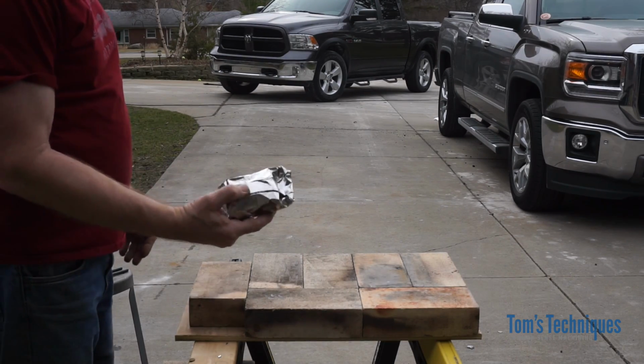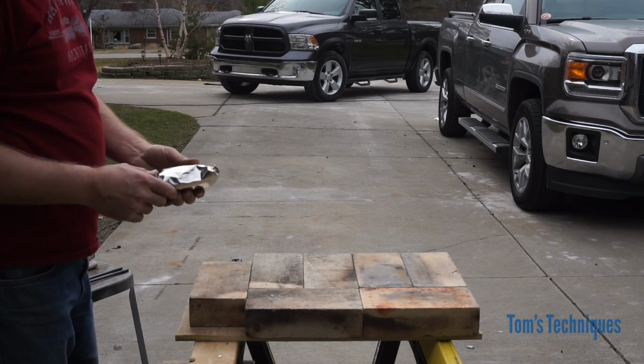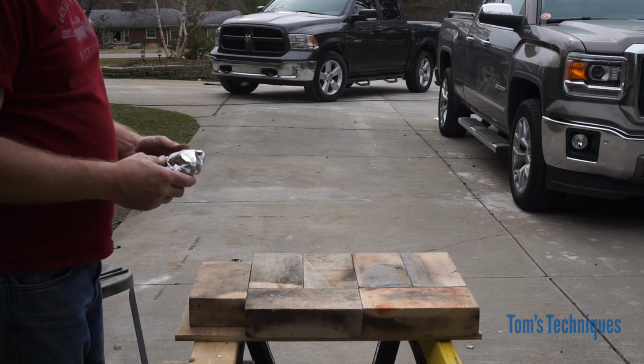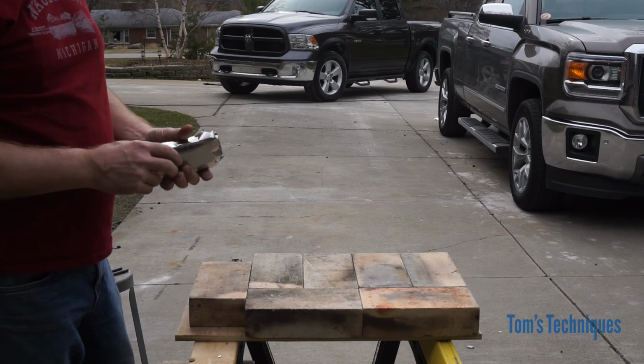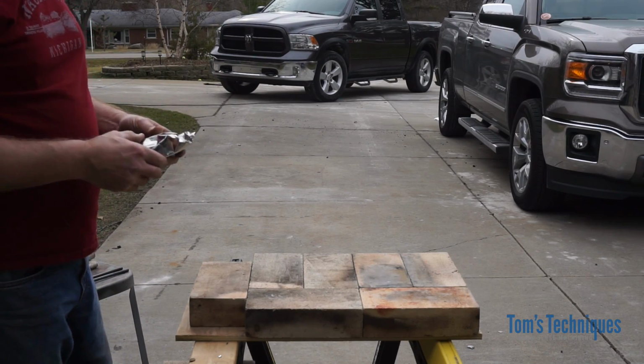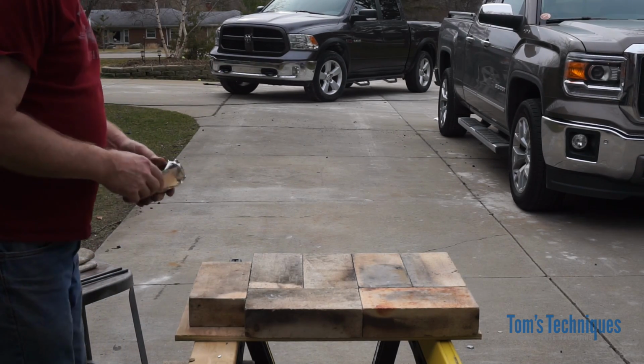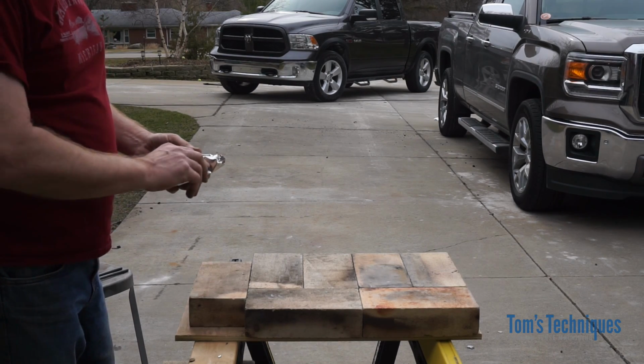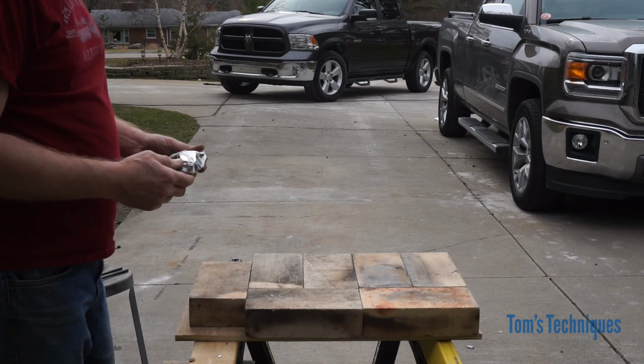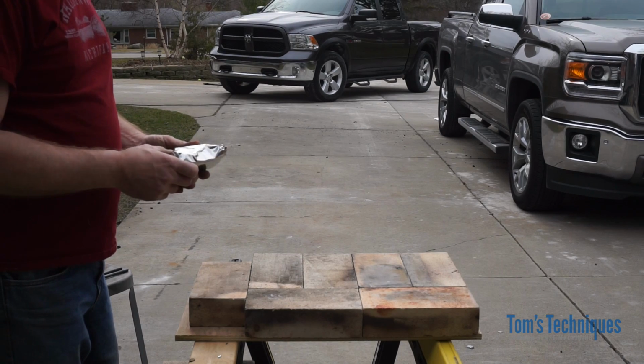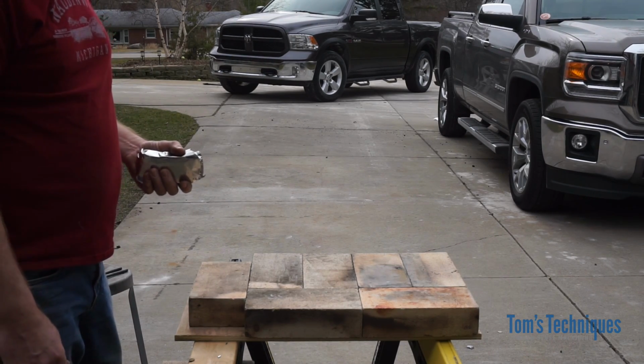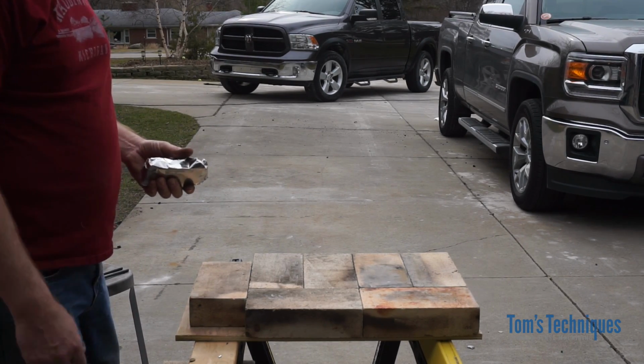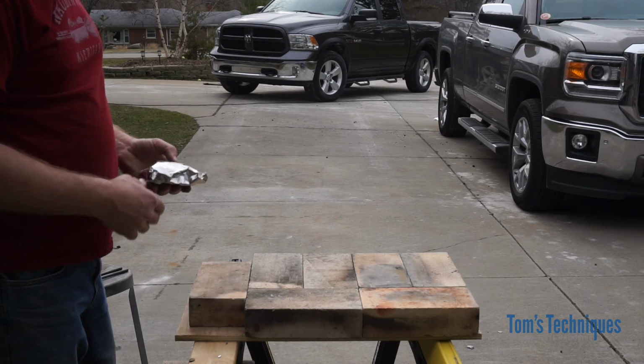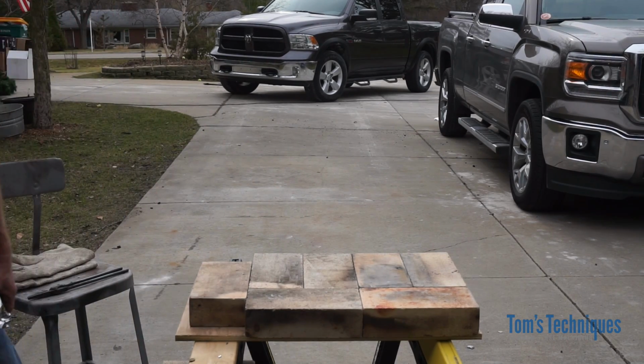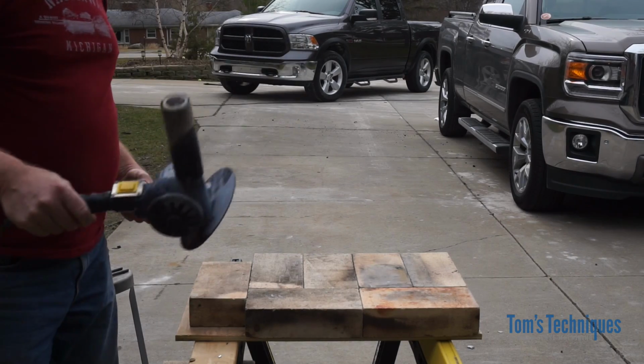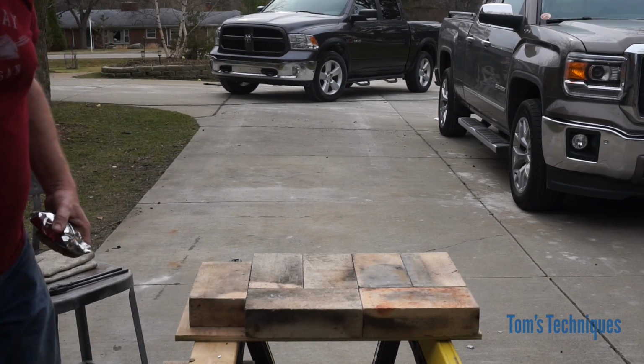Okay, so we have our parts all wrapped up in the carburizing compound. Now we need to figure out how to get them hot. They need to be between 1500 and 1600 degrees for 45 minutes or so. If I were doing that myself, I have an electric heat treat furnace that I would use. It's pretty easy to do, but not everyone has one. So I came up with an alternative method, just a forced air charcoal furnace. Charcoal's the fuel, and I use my trusty Harbor Freight heat gun to fan the flames, so to speak.